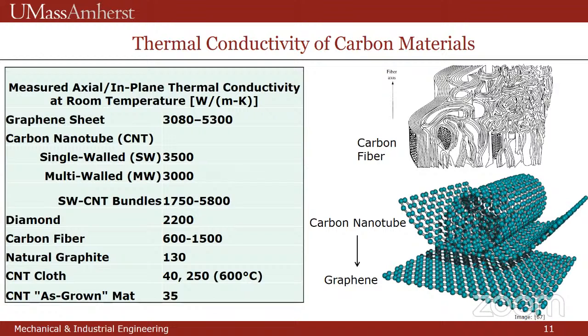So we looked at applying high thermal conductivity materials. And so you hear a lot about graphene, very high thermal conductivity, but it comes in sheets that are only 1 molecule thick. And a big graphene domain might be, I think, a few microns. There may be some that are 100 microns at research scale. The next level is carbon nanotubes that still are very exciting, but they have the same issue as well. A very big multi-walled carbon nanotube might be hundreds of microns long and a few tens or hundreds of nanometers in diameter. And all of these interfaces between the parts scatter phonons, and so they reduce the thermal conductivity of a big part.